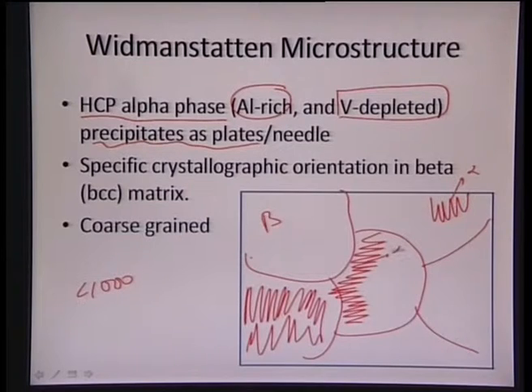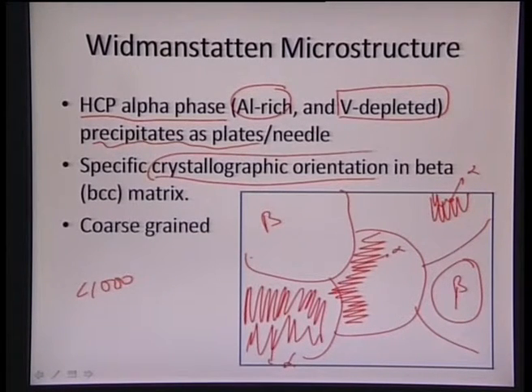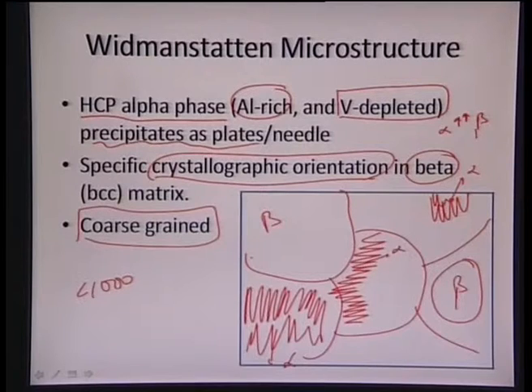So we will have many more regions which have started forming alpha, and then the original beta regions which were present because we had taken the material above 1000 degrees centigrade. So this is the initial beta, and then we start seeing the formation of alpha structure, which is much more needle-like, and that induces specific crystallographic orientation in beta. So this alpha is forming by precipitating in a particular crystallographic orientation. That is the reason it comes more like a needle-like structure, forming within the beta grain. So we have alpha getting precipitated in certain directions of the beta phase. That is what is being observed here, and it is again a coarse-grained material because the material has been staying for the whole heat treatment for a couple of hours. So that is the problem with this particular material.